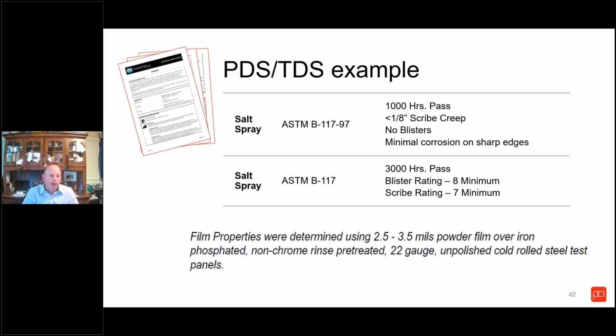In this example, state film properties were determined using 2.5 to 3.5 mils of powder, iron phosphated, non-chrome rinse, pre-treated, 22 gauge, unpolished, cold rolled steel panel. It may say it's an aluminum panel, it may say it's a B1000. But if you're comparing products and how they'll perform, it's important to make sure that you're looking at an apples to apples comparison.